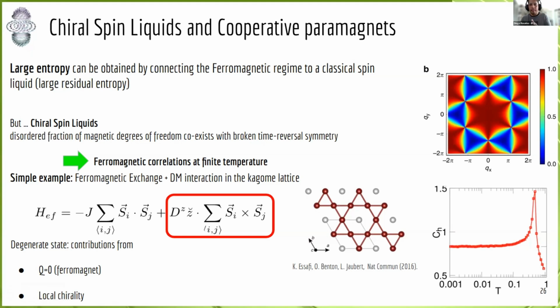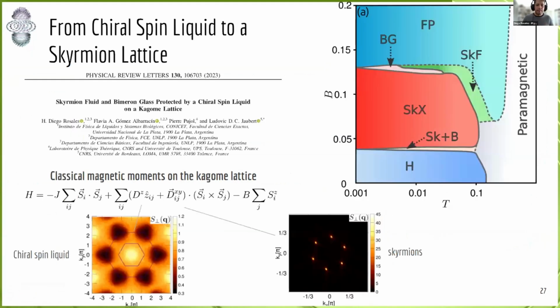It's a ferromagnetic state disorder with dipolar correlation. This is a really strange situation. Then we combine these two ingredients in this Hamiltonian. The first part is responsible for the spin liquid state, the chiral spin liquid state here, where you can see the pinch point, plus the skyrmion part related to the presence of triple-Q structure or Bragg peaks at